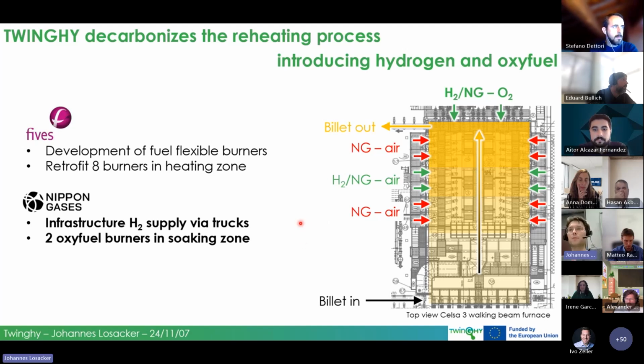Of course, we have to be able to supply the hydrogen to the furnace, which is actually a major challenge because we don't have a grid like we do have for natural gas. So our project partner Nippon Gases is taking care of the infrastructure that is required to get the hydrogen to the furnace, which is done within this project via trucks. At least 2 trucks are able to connect to the piping system that is then introduced by Nippon Gases to the furnace. And then we are able to operate the furnace, at least for a couple of hours for our test trials on hydrogen. Moreover, Nippon Gases is introducing 2 additional burners.